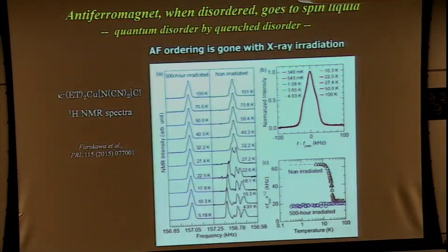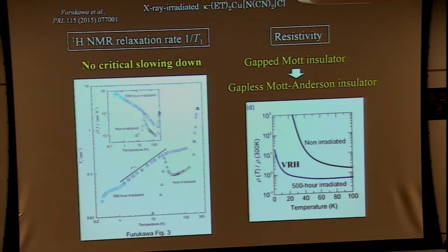Okay, this is the NMR data. This is the NMR spectra before X-ray irradiation, and after irradiation the NMR spectra shows no change down to 340 millikelvin. This is the spectra superposed. All of the spectra are nearly the same. So before X-ray irradiation, the NMR spectra shows a clear splitting, the magnetic ordering, but this magnetic ordering is completely gone by introducing disorder to the system. It's a very curious and interesting feature.